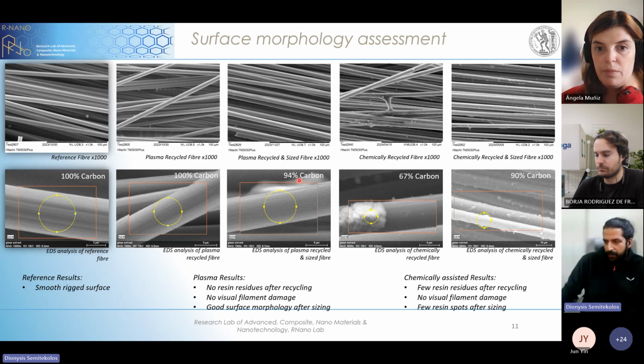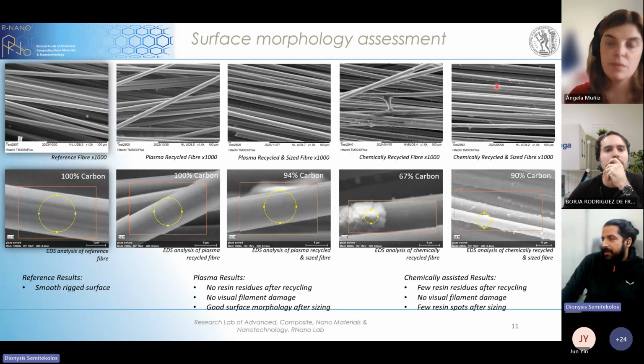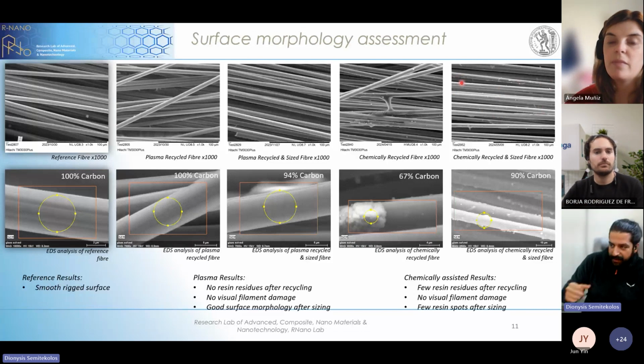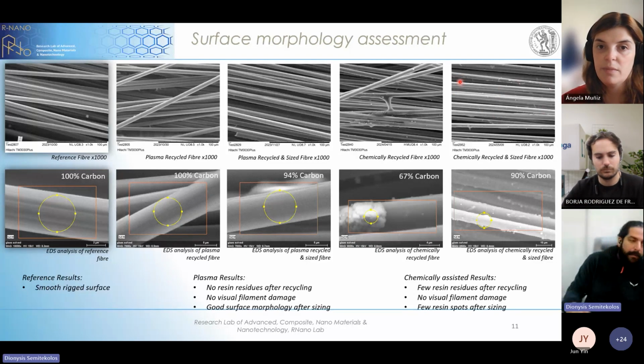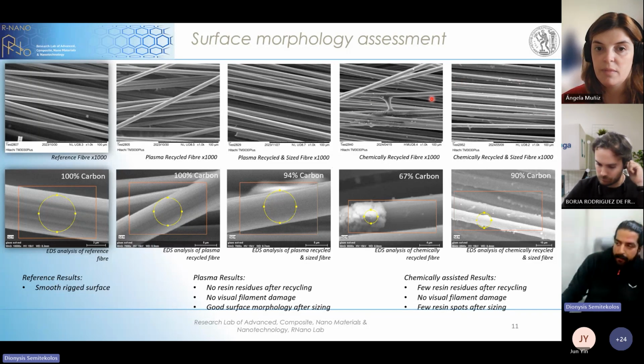So here we see we have some visual contact with residues that come from some parts of the chemically recycled fiber, and we can also confirm this from the EDX analysis. And this affects the morphology of the fiber after the sizing. So we see that there are some residues even after the sizing. However, both processes showed very good results, and these are just some parts that we chose to show you how a non 100% clean fiber looks like.